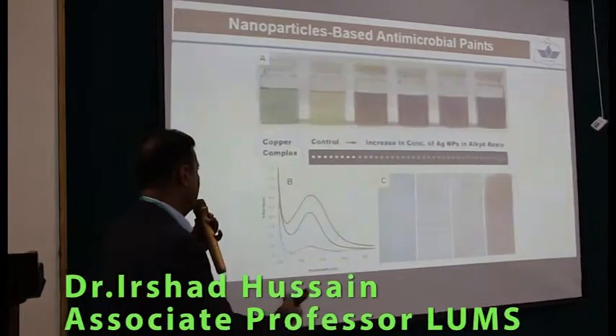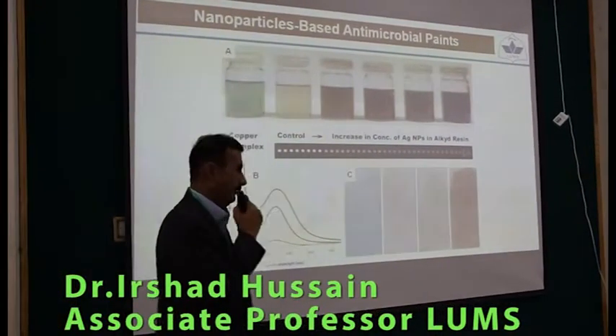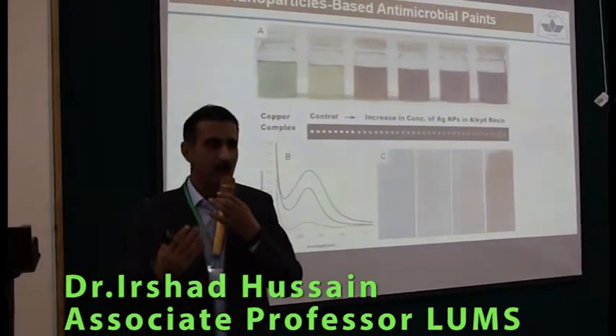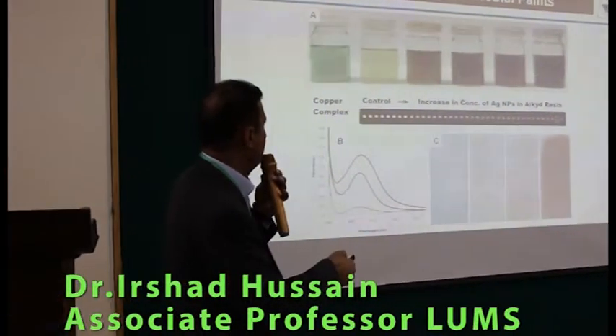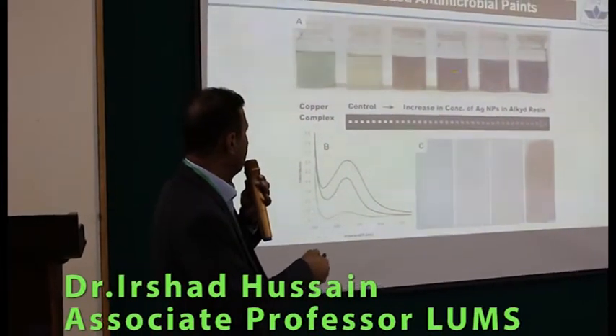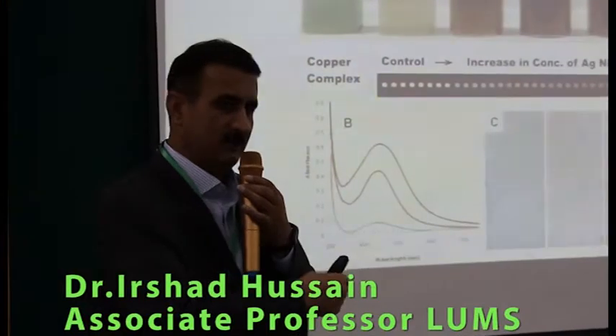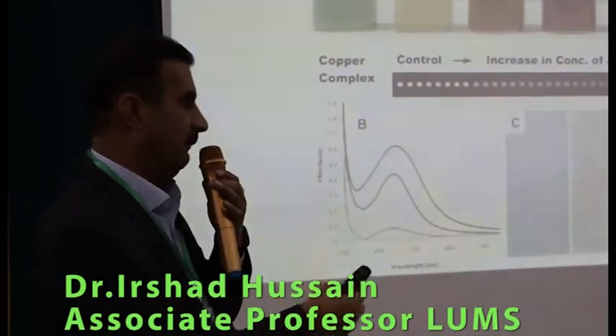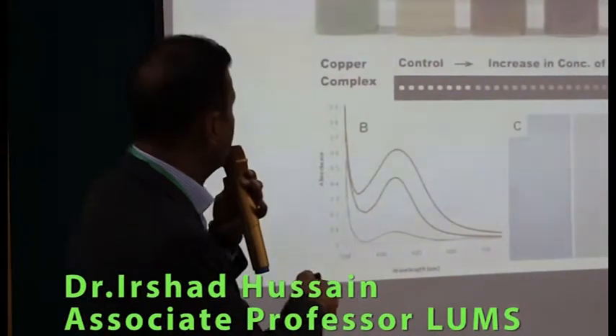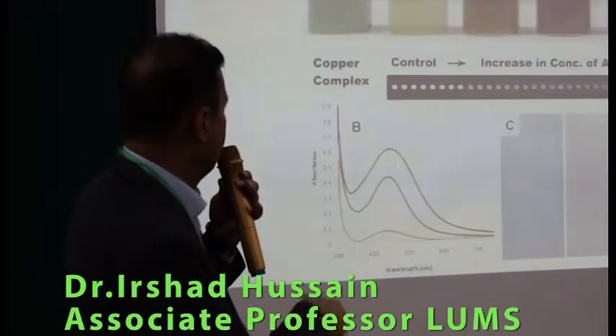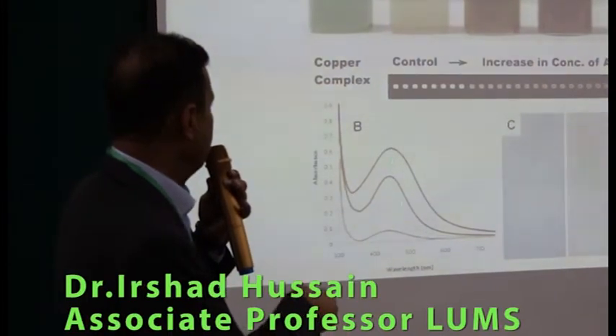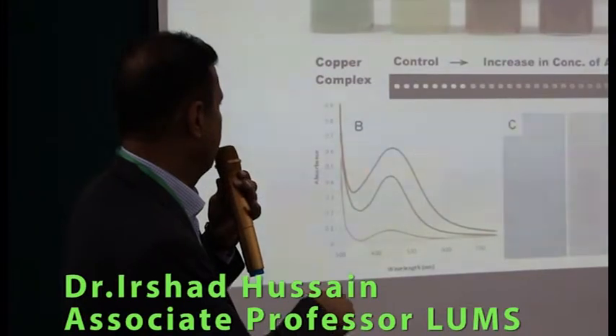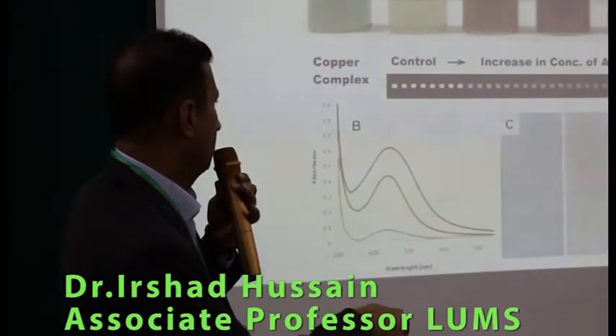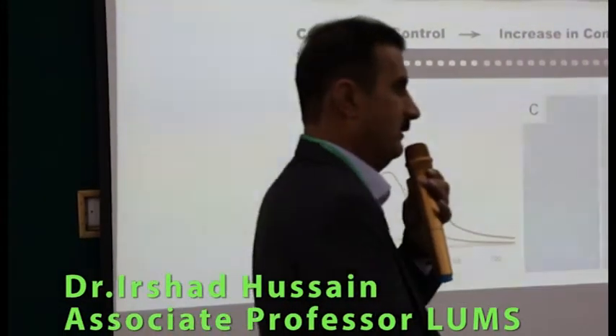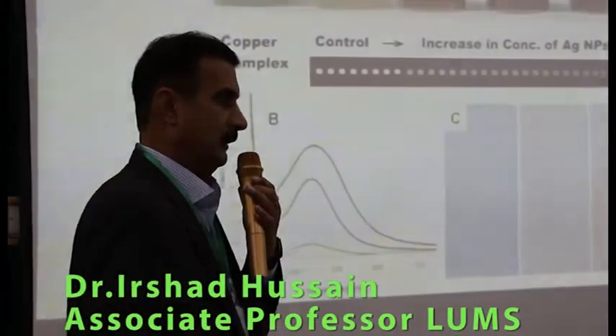So we are also working with some industry, textile industry and actually paint industry to develop antimicrobial materials as well. This is just an example of antimicrobial paints. So we take the resins which are produced by our local industry, and without using any additional chemicals, starting from commercial silver, you can produce silver nanoparticles. And this band simply shows that we are increasing the concentration of silver nanoparticles as we go. So we are able to control this. And they can be painted in hospitals so that bacteria cannot contaminate different surfaces. So this was all about biomedical.